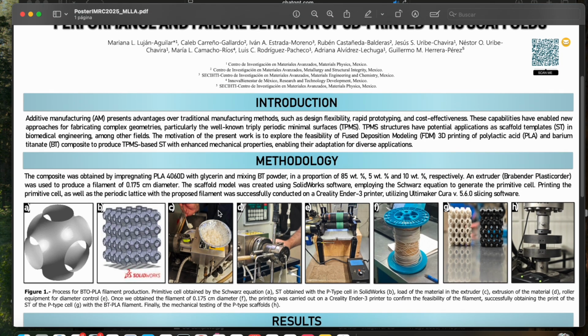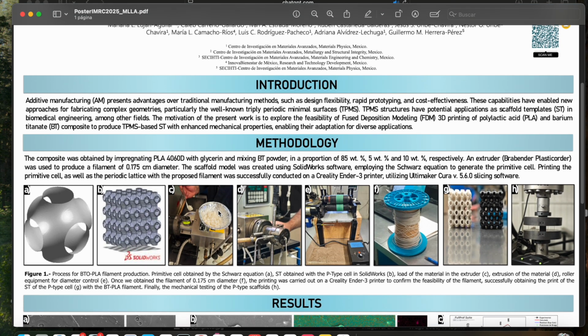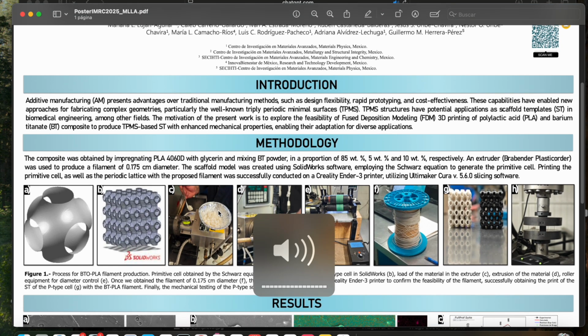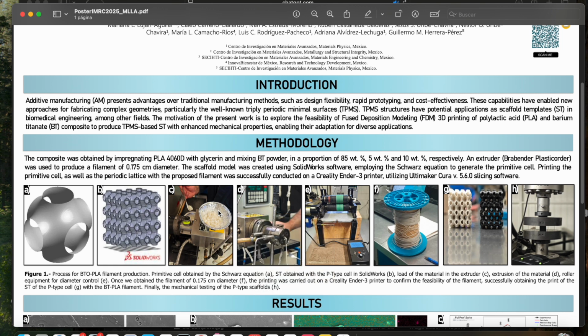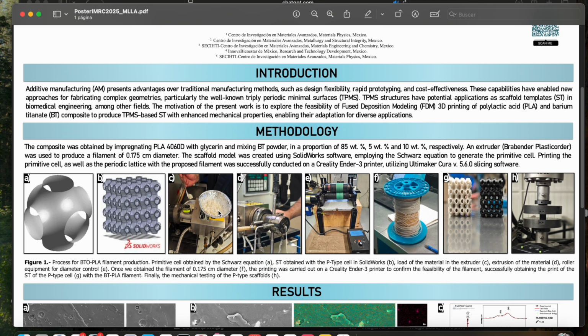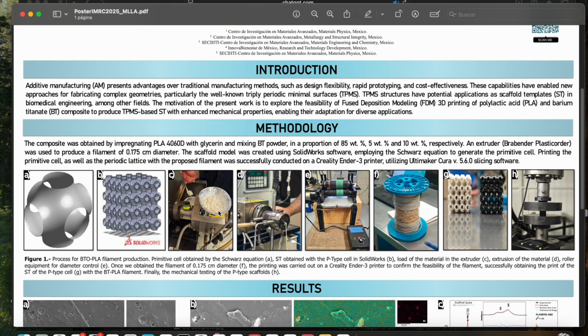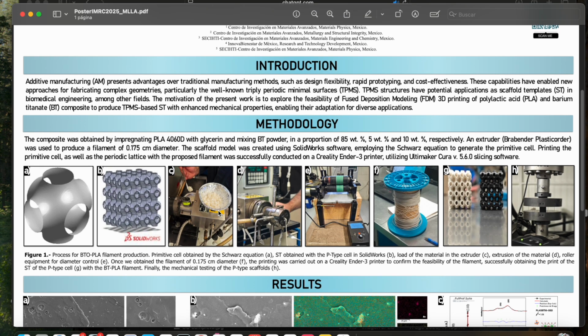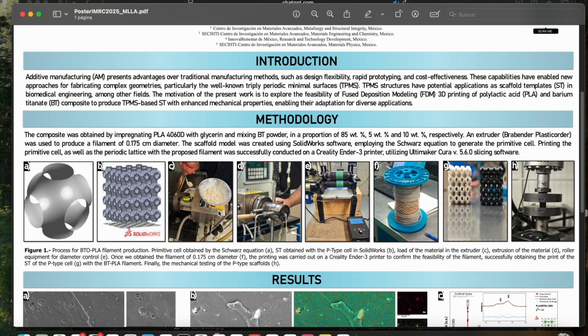We impregnated PLA 4060D with glycerin and incorporated BaTiO3 powder to reach 85 wt% PLA, 10 wt% BT, and 5 wt% glycerin. The blend was hot mixed and extruded in a Brabender Plasti-Corder into 1.75 millimeter diameter filament, then sliced in Cura 5.6 and printed on a Creality Ender 3.